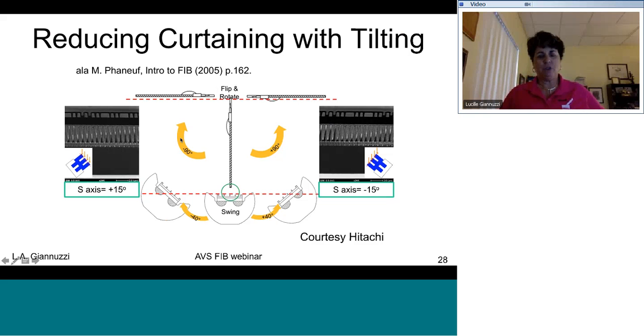Basically, it consists of coming in to the sample surface at different tilts with the ion beam. So conventionally, you would be FIB milling parallel to these lines. So it's a way to rotate and tilt such that you come in at 2 different angles. Or if it's a semiconductor sample like this, you can mount the sample upside down in the so-called backside configuration and mill from the substrate side. Then you don't get curtaining in the substrate, but of course you'll get curtaining in anything in the metal layers. But that usually is not a concern.